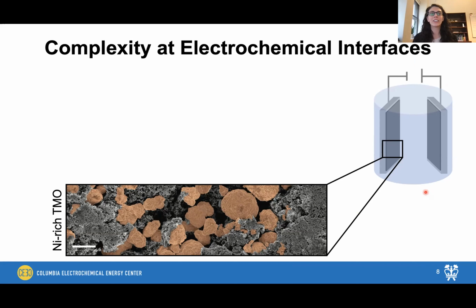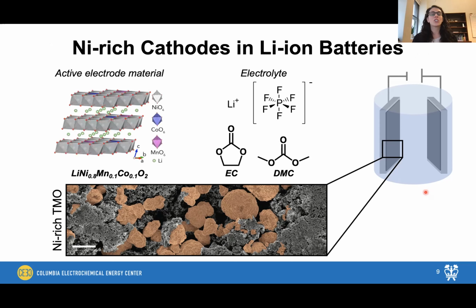So what you're looking at here is a nickel-rich transition metal oxide active particle shown in orange, and then our carbon additives, so our conductive carbon and our polymeric binder, are shown here in gray. So the system that we're going to be talking about today is the lithium nickel manganese cobalt oxide active particles. Those are actually what's shown in the SEM image here. This is abbreviated NMC811. That's what you'll hear me talk about for the remainder of the talk today.